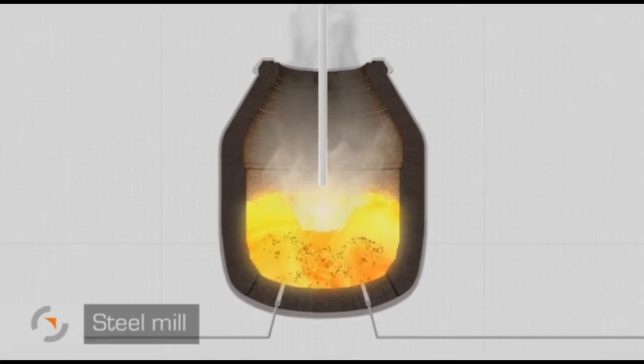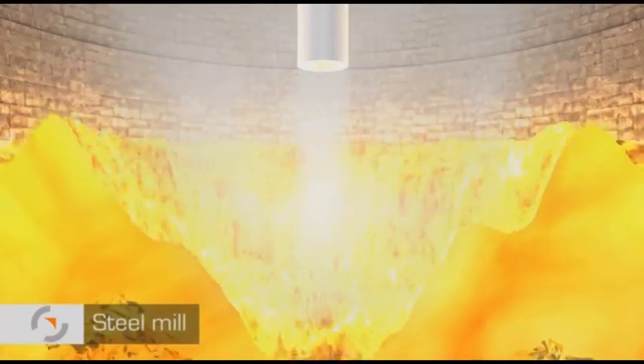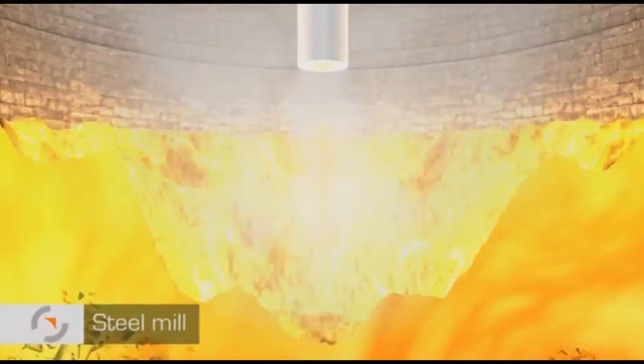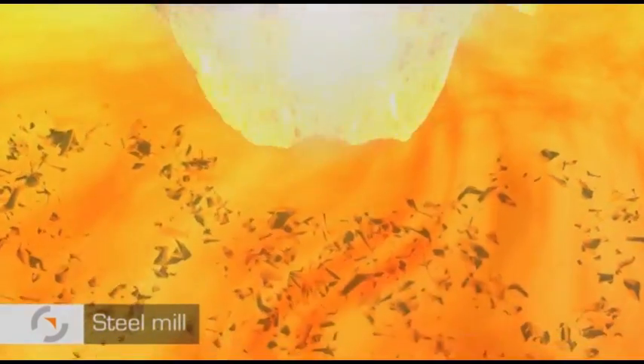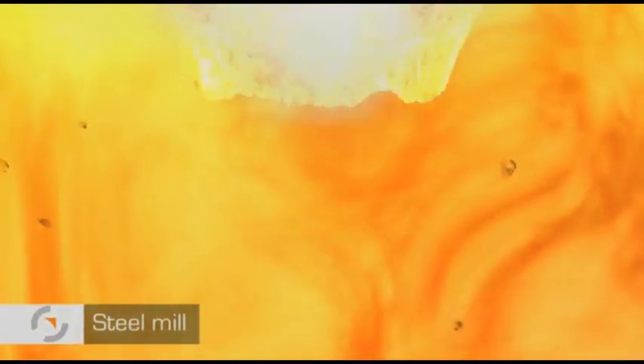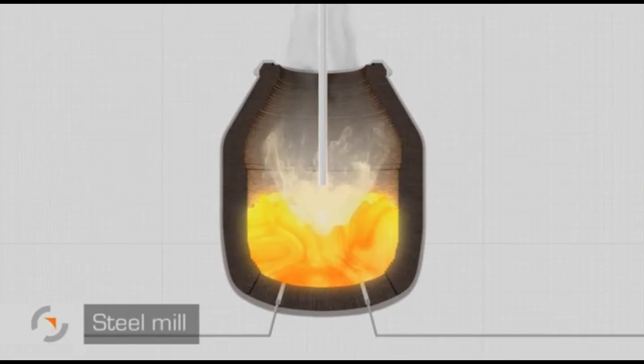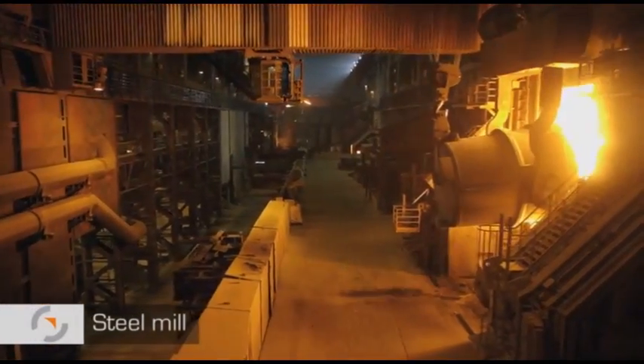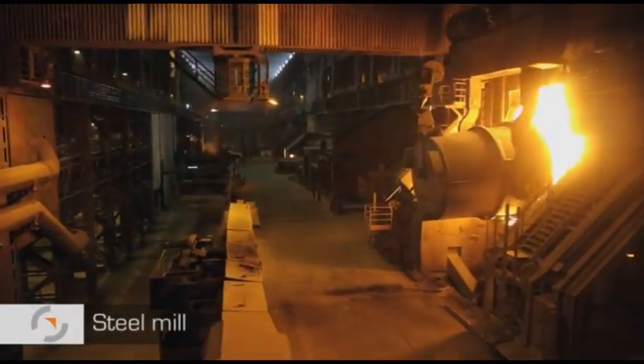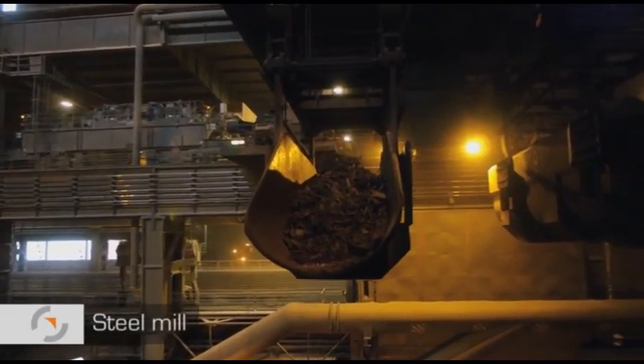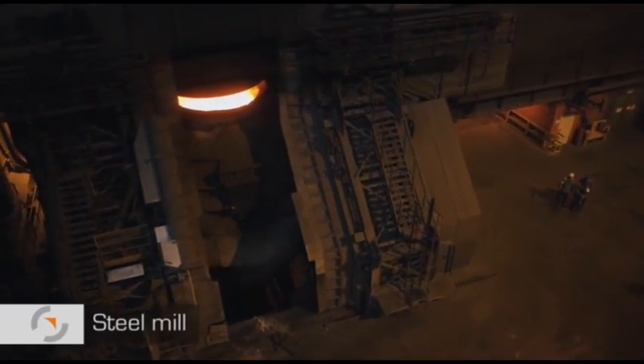Extremely high temperatures of up to 3,000 degrees can theoretically be generated. To prevent this, the converter is filled with chill scrap. As a result, at the end of the converter process, the temperature is about 1,700 degrees. In total, the converter process takes about 40 minutes, and at the end of it, the pig iron has been converted into crude steel. Each of the 3 converters has a capacity of 220 tons. Up to 12,500 tons of crude steel are produced at the Salzgitter site each day.